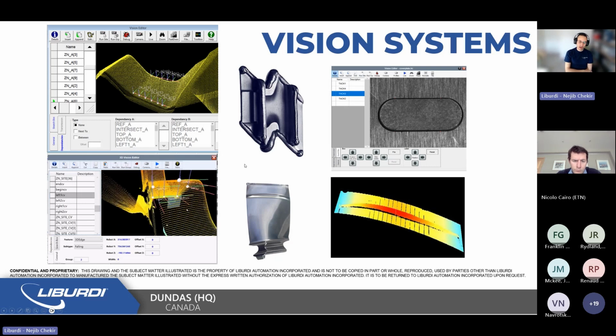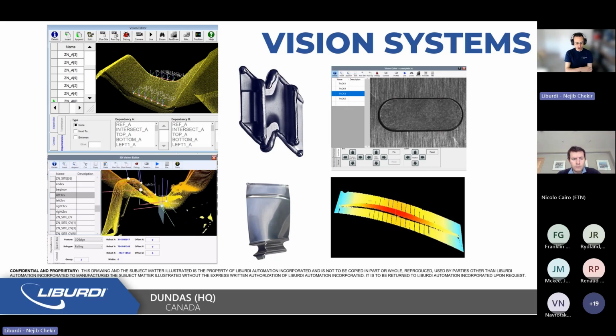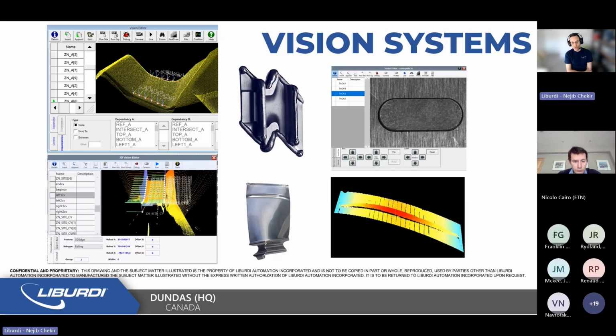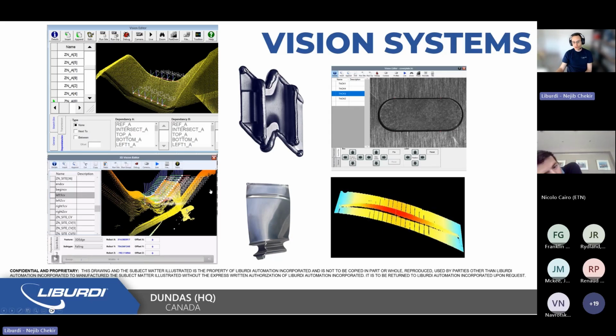And again, after calibrating this scanner to the torch tip position, what you can do is then generate these sites of interest that have not only the XYZ component in them, but you can include as well other degrees of freedom if they're relevant in this case, and that can include something like a rotary and tilt that teaches the weld head where to go. And by generating all these sites, then the robot will know where to go in space and to precisely position the weld head and complete the repair of the part of interest. So 2 examples here. There are a few other methods, also more manual methods, but this is what enables us to teach the robots where to go in space.